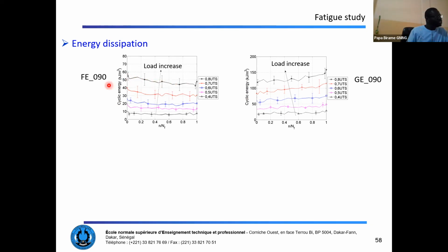But throughout the life of the flax epoxy composite, we can see that the size of the hysteresis loops is diminishing. In the early cycles, you have higher, more important energy enclosed in the hysteresis loops than at the end of life. What differs for the glass epoxy 0/90 composite is that the size of the hysteresis loop is quite small at the beginning and increases. That means that the glass epoxy dissipates more energy at its end of life than the flax epoxy, which has a kind of self-healing during its fatigue loading.